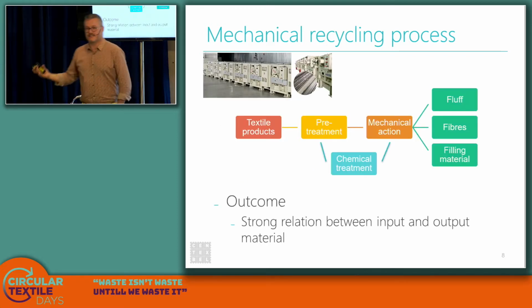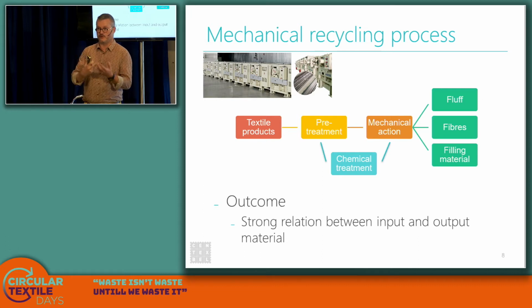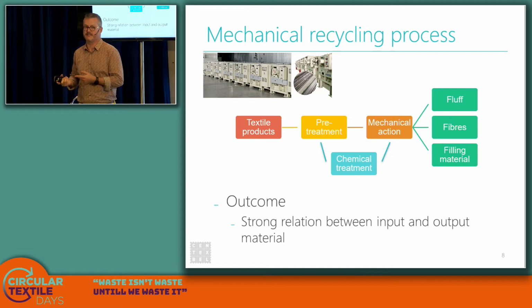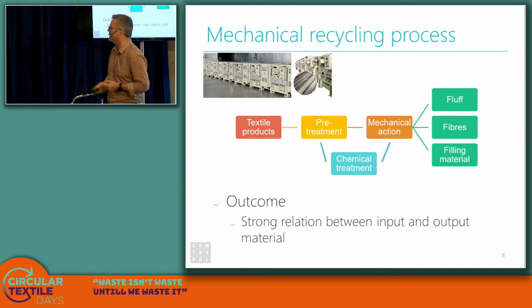What do you do? Actually, you shred open the textiles and you regain fibers. You regain short fibers and long fibers. The long fibers you can spin with. The short fibers you can use for fluff production. And then you have small particles that come out. If you are grinding, then you have only small particles that can be used for filling material, or, importantly, they could be used for other technologies as an input material. And this is not really done at the moment.